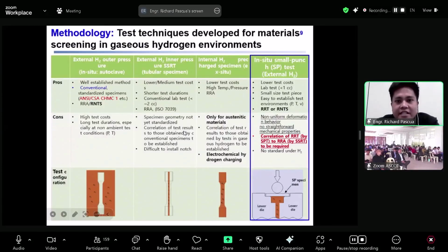There are several techniques that have been developed for screening materials in gaseous hydrogen environments, but in this study we mainly focus on a simple testing technique, the small punch test under an external hydrogen environment, in which this method involves a compressive test where one side surface of the specimen is directly exposed to the external hydrogen environment during loading.